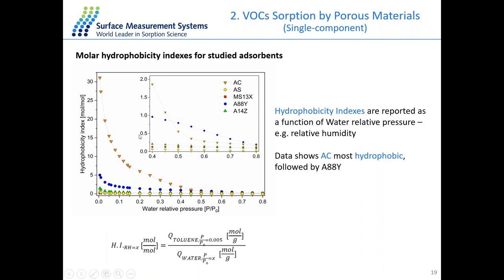From this result, the orange dot here, which is the activated charcoal, the AC sample, seems to be the most hydrophobic adsorbent. This is followed by the blue points here, for the A88Y, the zeolite Y sample. But one highlight in the high humidity range is that you can see the blue line is sometimes above the orange line. That may explain why sometimes at higher humidity, the zeolite Y sample could be a better choice than the charcoal sample. So these are all based on the single component experiment.